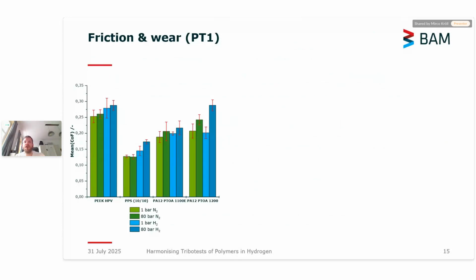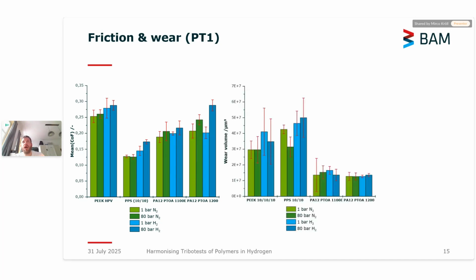Some friction and wear data of our PT1 tribometer of the compounds that we used. The mean coefficient of friction is plotted here, and we can see that not every material reacts to hydrogen and higher pressure the same way. So there's no general rule that hydrogen is increasing or decreasing friction. The same goes for the wear volume, and you can see here there's a huge standard deviation between the tests. I said 4 repetitions, so this is the standard deviation of those 4 tests. And you see that especially for those that are fiber reinforced, the scattering is rather high. So we all know that wear is somewhat tricky to reproduce for polymers.